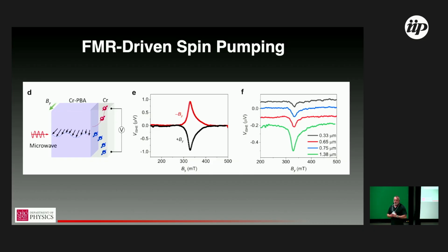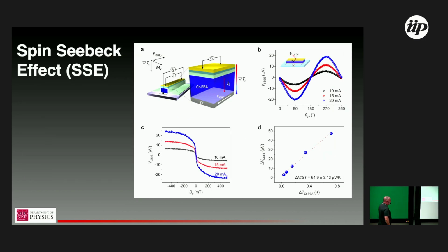This has been studied in lots of magnetic systems, but the size of the signal here is large for a messy system. It goes a bit against expectation. You can do essentially the same physics with a temperature gradient. Again, you're just taking the magnons out of equilibrium. That creates a chemical potential difference, which in the presence of the thermal gradient generates a similar inverse spin Hall signal. You can see the size of that signal is actually quite large for the field, tens of microvolts. So these exotic systems not only show measurable effects in this regime, but ones that can be large and impactful.